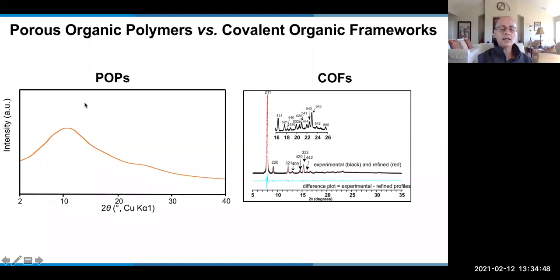There's a class of materials that have emerged from using the reactions that we've developed for COFs, but they are not crystalline. They are not produced as crystalline materials. These are called POPs, or porous organic polymers. Now you see this all over the literature. POPs are made under the same conditions as COFs. They are made using building blocks that we made COFs from. And so they are based on the chemistry that we developed in COF. But then they are amorphous, or they are poorly crystalline. And I would say that a POP is really an ill-crystallized COF, or a poorly crystallized COF. So in fact, in my group, for every COF that we crystallize, we probably produce tens of POPs, okay?